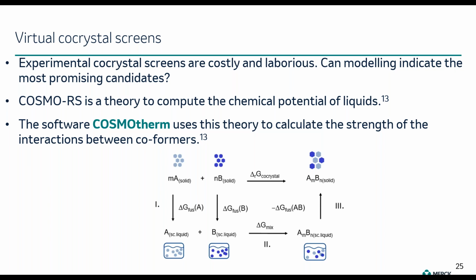The idea behind this approach is that the strength of the interaction between two co-formers in the solid state, which will determine whether or not they will form a co-crystal, can be approximated by the energy of the interaction of the two co-formers in the liquid state, in a supercooled liquid state. And the idea is to calculate an energy of mixing, which is a measure of how much two co-formers prefer to stay together rather than separate. And the lower this energy of mixing in the supercooled liquid state is predicted to be, the more two molecules are predicted to like to be together, and so the better co-crystal co-former they are predicted to be.